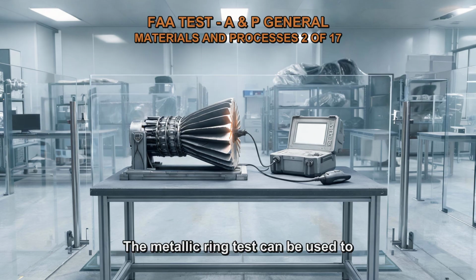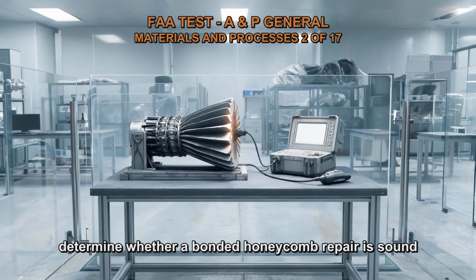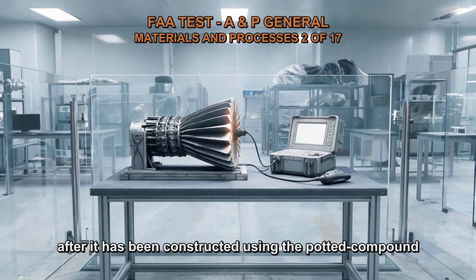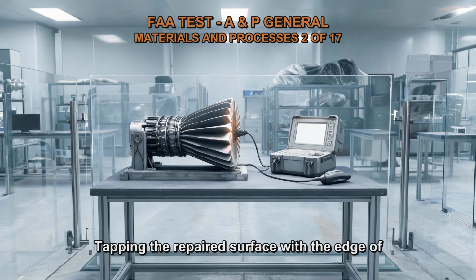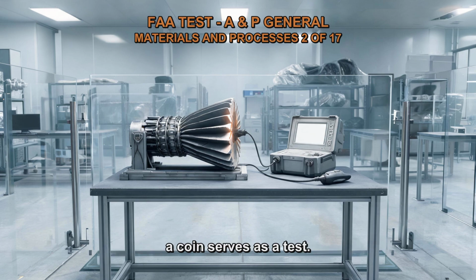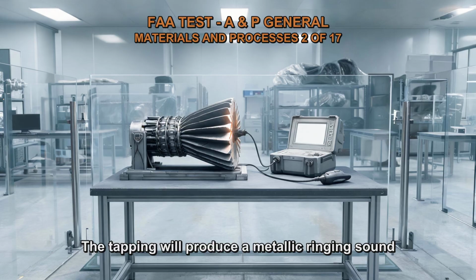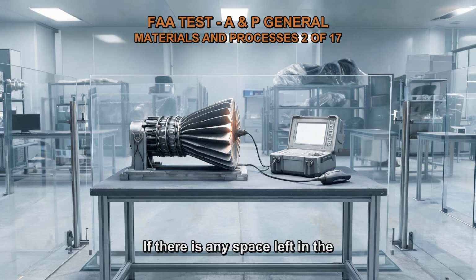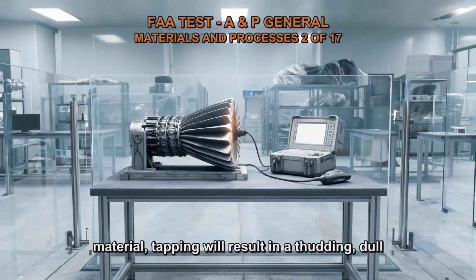The metallic ring test can be used to determine whether a bonded honeycomb repair is sound after it has been constructed using the potted compound repair method. Tapping the repaired surface with the edge of a coin serves as a test. The tapping will produce a metallic ringing sound if the repair is sound. If there is any space left in the material, tapping will result in a thudding, dull sound.